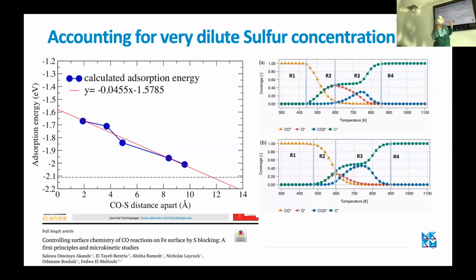When we introduce sulfur, what we see is that we are slowing down. This is the phase where CO decomposition is happening at around 420, and it's shifted to approximately 470. Then the decomposition starts much later, which means that the availability of carbon or CO on the surface is much less, which is due to the effect of sulfur. And this is how we could explain how H2S, at the end of the day, is retarding the metal dusting corrosion in this case. Okay.